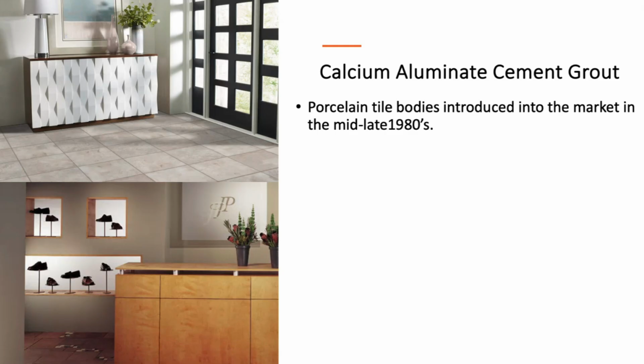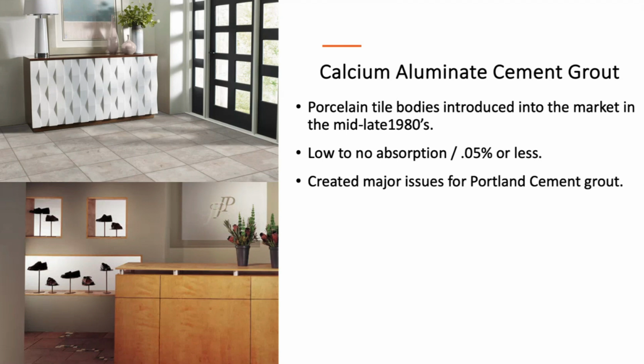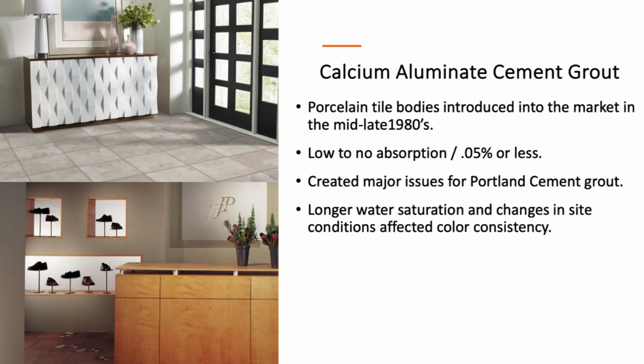So what we get with the calcium aluminate cement. Porcelain tile started coming out in mid to late 80s. There's low to no absorption. So it's a 0.05% or less. So that created major issues for Portland cement grouts. The longer water saturation, because of the no absorption on the side, what we discussed, the longer the water saturation was in there, changes in the color conditions, and it affected the color consistency.